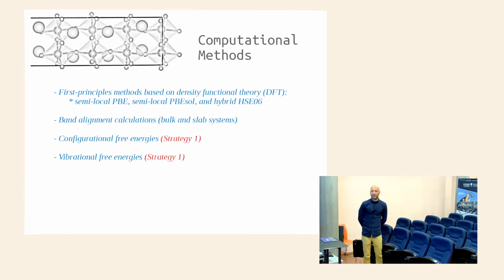But for the work related to strategy one, which is about mixing, the DFT calculations are based on particular approximations, so PBE and PBEsol, and also some hybrid functional potentials. What I'm going to be doing basically is band alignment calculations, configurational free energy calculations, and vibrational free energy calculations. So I'm going to deal directly with temperature, which is something that most of the time we don't see in this kind of first-principles works.